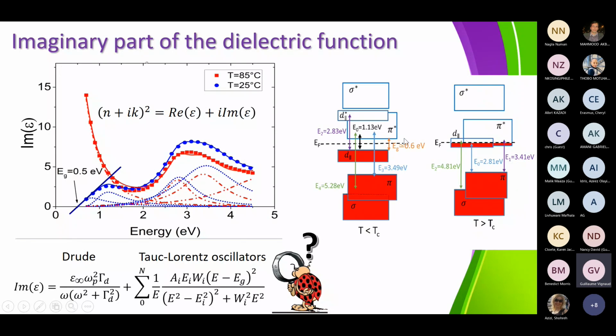typically when you do the fit in the insulating phase, you get a gap value of the order of 0.6 electron volt. But additionally, from all the positions of the bumps, you get other values, and those values are related to the interband transitions between the electrons coming from the d band of the vanadium and from the sigma and pi bonds of the oxygen. Okay, and so you can fully describe what's going on in terms of energy in your material.